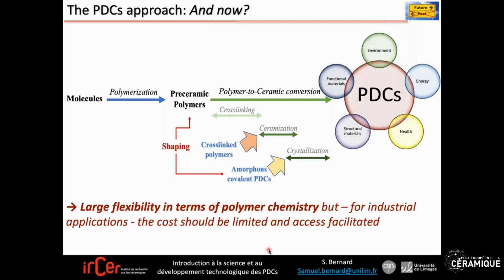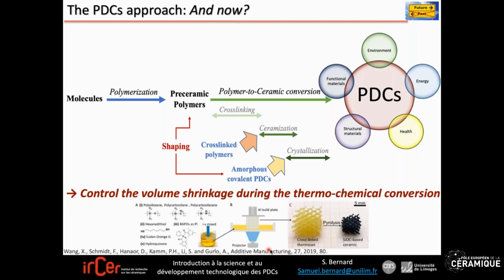There is a key issue of PDCs. You can clearly see on this image the volume shrinkage that occurs during the polymer to ceramic conversion. It usually represents more than 50%. So you should know this before preparing your materials.